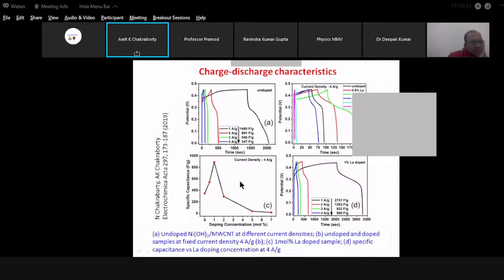So if you plot the specific capacitance at 4 ampere per gram current density, we see that the highest specific capacitance is obtained at 1% doping, which is consistent with the CV results. CV and GCD conform to each other, and we have shown here, further, at 1% lanthanum doping, the influence of different current densities. As usual, the highest current density gives us the lowest value of the specific capacitance. So then what is next?